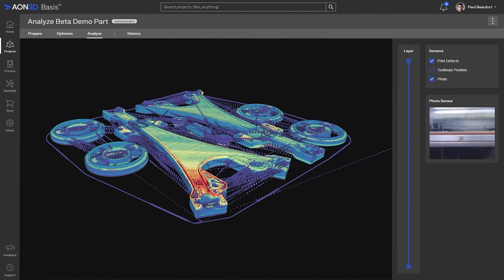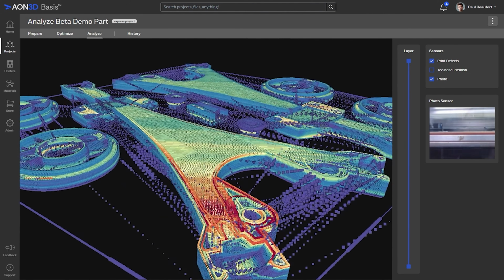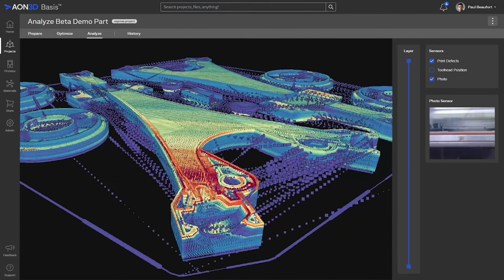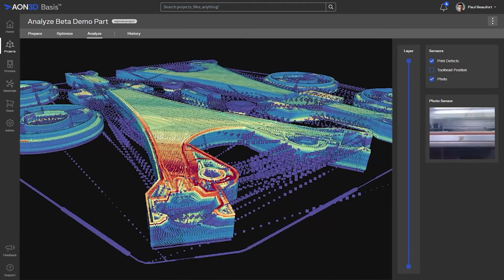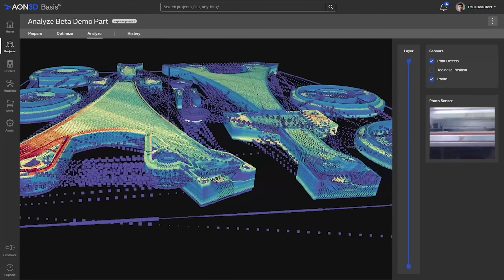And now we can see that there might be a problematic area within this print, right? Maybe it was a material feedstock issue where it was way over diameter and we did not have diameter flow compensation turned on. If it was a smaller dot, it could have been a piece of dross or unwanted material inclusion within the print, creating that high spot. This really gives you an interesting amount of part quality data.